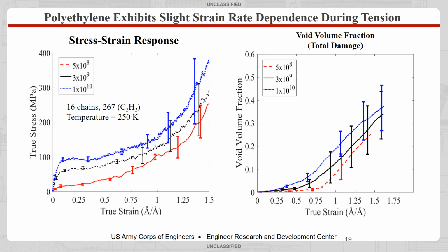as mentioned earlier. So here we see that the yield stress is indeed quite highly strain rate dependent in polyethylene. But you'll notice that post the yield, the shape of these stress strain curves are very similar. So there's not much strain rate dependence in what's occurring in these plasticity events, things like chain alignment and damage, and that's evident here in this void volume fraction. So this elbow is strain rate dependent, but post that you have very similar responses, and you have a lot of overlap with these uncertainties.